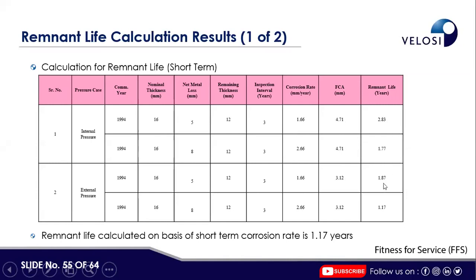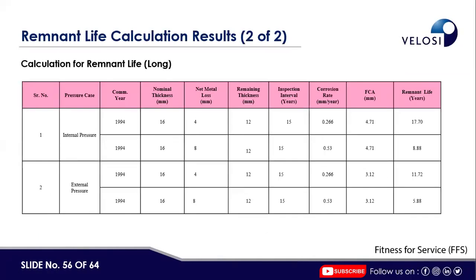So these are the short-term remnant life: only 1.87 years or 1.17 years remnant life was reported as minimum. If the metal loss is on a long-term basis, like this metal loss took place during the last 24 years of service, in that scenario more future life was available because the corrosion rate was reduced to 0.266, 0.53, 0.266 and 0.53 mm per year. So the minimum life was 5.88 years. Now that is a situation where management or the inspection and corrosion team need to decide how they will be managing this equipment. If the damage is short term, then they have to retire the equipment or take some more preventive measures. But if the corrosion was long term, then they have some more room to manage the equipment.